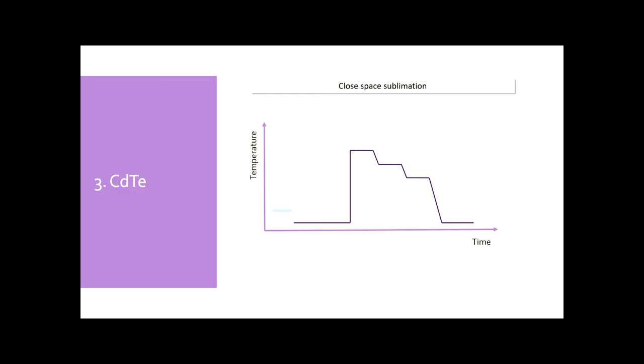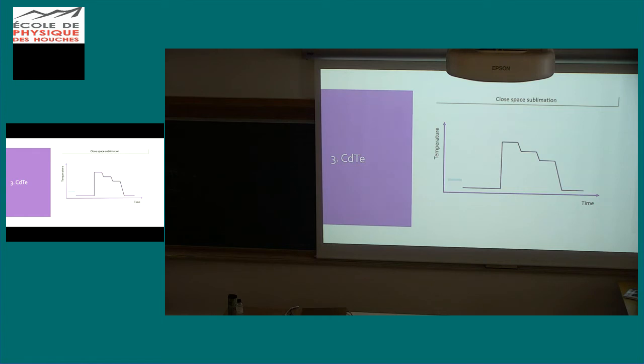I'm basically summarizing the production of cadmium telluride. You start with just a substrate with FTO, for example. Then you sputter zinc tin oxide and cadmium sulfide, and then you immediately increase the temperature to deposit the cadmium telluride. Then you reduce the temperature a bit for the cadmium chloride treatment, and reduce further for the sputter of zinc telluride copper contact. Then you sputter some metal to improve the conduction. Normally aluminium can be used, and then it's done. This is a very fast and cheap process.